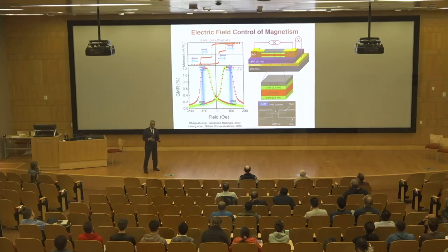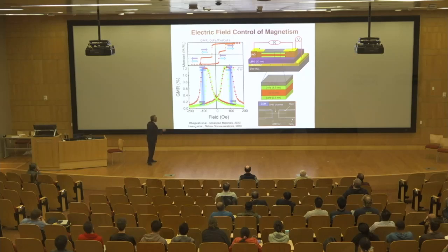Okay, that brings us to a key piece of data, which took us a while to get to because we wanted to make sure that we actually got this right. So if you take this bismuth ferrite layer, which is here, and put a spin valve, which is a metal ferromagnet, on top of it, the ferromagnet at the bottom will couple magnetically to the multiferroic. And in doing so, you will create something called a GMR, a giant magnetoresistance spin valve.